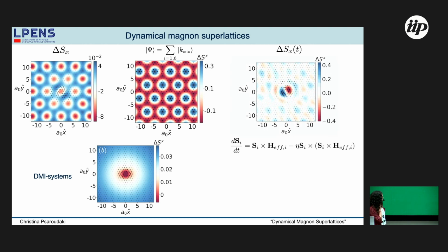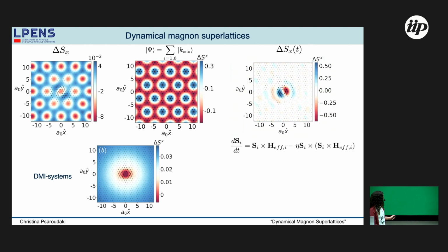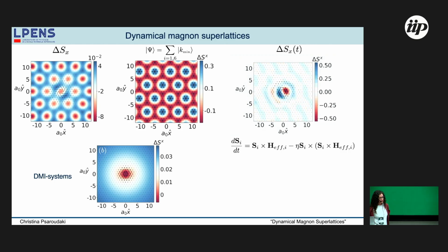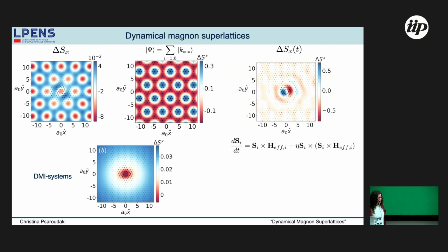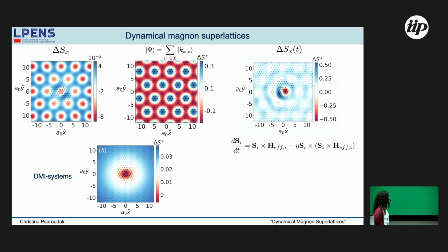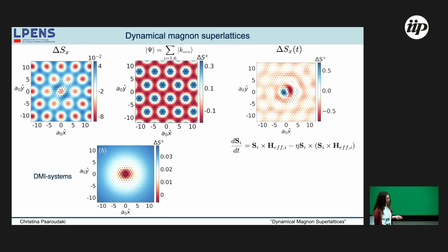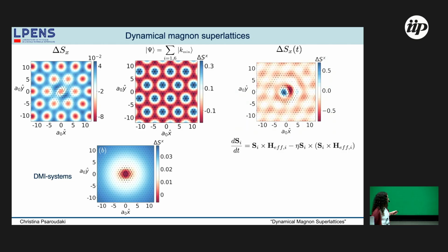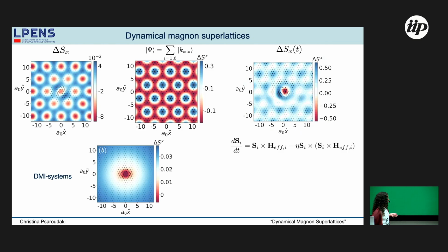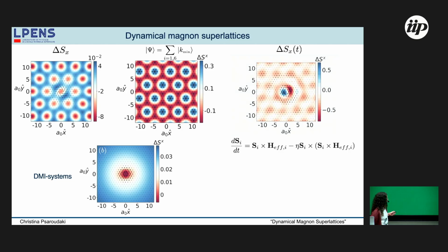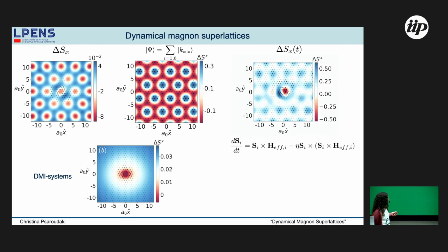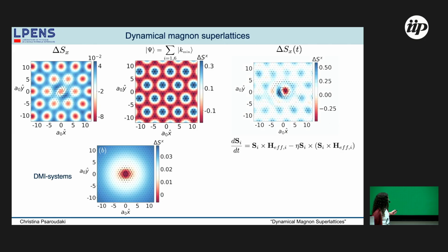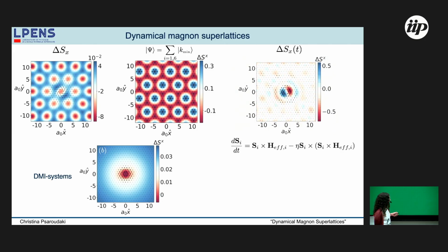And then we ask the question whether these superlattices or this skyrmion can be observed experimentally, or dynamically. So can we activate this supermode? If we start from a simple ferromagnet, we put in-plane or out-of-plane field, we cannot reach a state where we have a superposition of those extended states, giving rise to these patterns. But if we put a skyrmion in, the skyrmion gyrotropic mode is superimposed with these extended states.